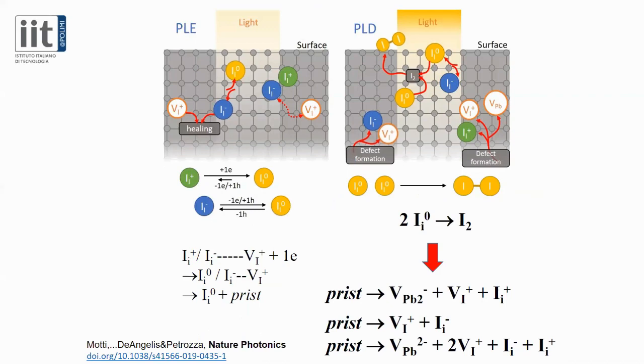When we trap an electron or hole, we reduce the activation energy for a Frenkel defect, where you see an interstitial and a vacancy close to each other, to collapse onto each other. This means that we are left with a reduced density of defects, and this can make us observe the healing phenomenon. And this I0 species is a metastable species, which will have the lifetime of the trapped carrier. So in a situation where we have a low density of defects or low illumination density, this I0 will then go back and release the carrier. But if we have a high density of I0, which means close to the surface, for example, where we have a high density of defects, or under high illumination intensity, I0 can go through a bimolecular process and form I2.